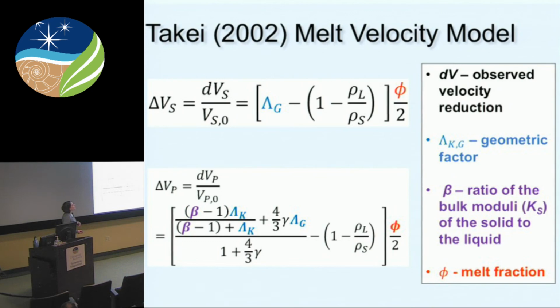So how do I go from velocity to things like melt fraction? To do that, I use Takei's model. She constructed an analytical solution where you can take the observed seismic velocity reductions, these delta V's and delta S's, and calculate what you would expect for melt fraction. These equations are actually fairly simple. They really only depend on a couple of things. One is melt fraction. This blue lambda parameter is controlled by melt geometry. And then we have this beta factor for the P-wave velocities, which is the ratio of the bulk modulus of the solid to the bulk modulus of the liquid.